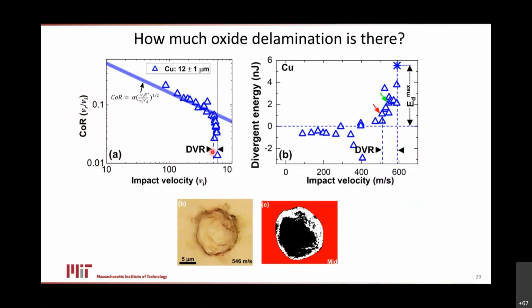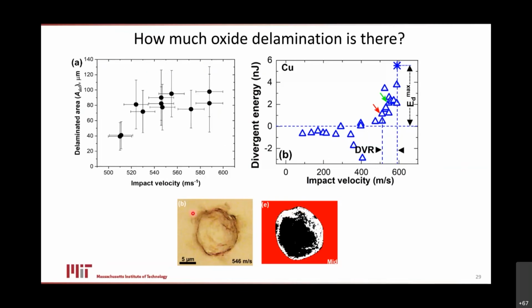So we're big fans of quantitative science, and so one of the things we've done is we've done a bunch of shots in this range, and we've gone in and tried to quantitatively measure the amount of delaminated oxide that we're seeing. And so we do some image processing. We've got an algorithm which can separate topography from color in these images, and so it can literally measure all the regions where it thinks there are flakes of oxide that have fallen off. And we can do that actually quantitatively and with error bars, which allows us to measure it.